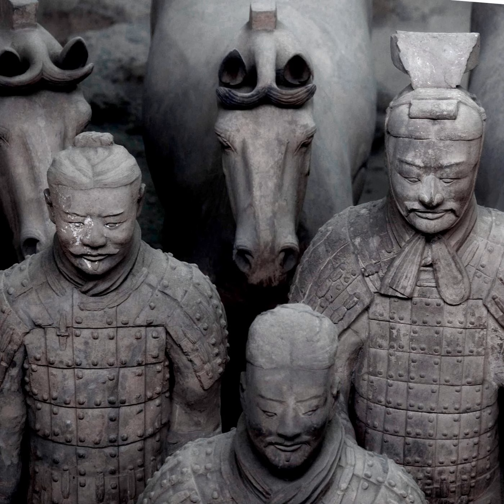But you don't want to rush through the oxidation stage. You need to make sure that all the carbon and all the sulfur and whatever else you can vaporize out of the clay is gone completely. So what you do normally is you stop the ramp. That is, you leave the temperature at a steady rate and not increase it past the oxidation temperature for a little while, right? Maybe an hour, maybe 3. A steady temperature like this is called a soak, right?